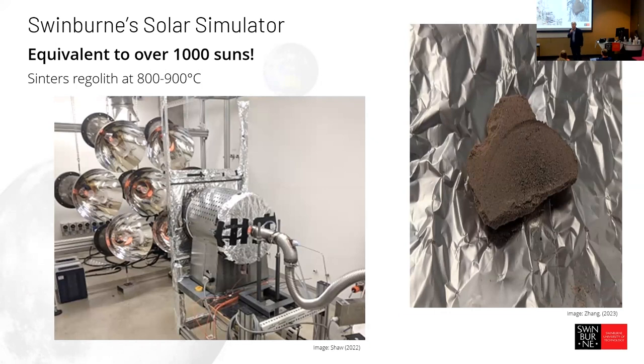Well, we don't run out and get a whole lot of mirrors and shine them all at one spot. We actually get cinema lamps to impersonate the sun. And this is the solar thermal facility at Swinburne. We can impersonate over 1,000 suns by shining 7 cinema lamps at one spot, right? And we can get well over 1,500 degrees C in that spot. We get some serious solar flux.